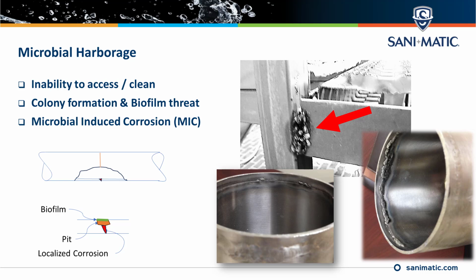And I've seen insides of pump casings that are very thick, and they've had MIC start, and it literally started channeling underneath the surface, and then all of a sudden parts of the surface of the stainless started flaking off, and now you've got patches of just awful. I mean, it literally almost looks like an ant farm started creating under the surface. This can also happen if you've got chloride stress corrosion cracking, which is where the stainless has been exposed to salts, high salt content at high temperature.